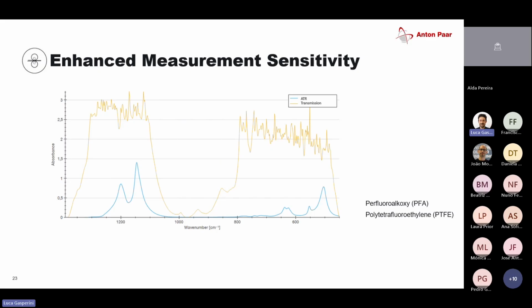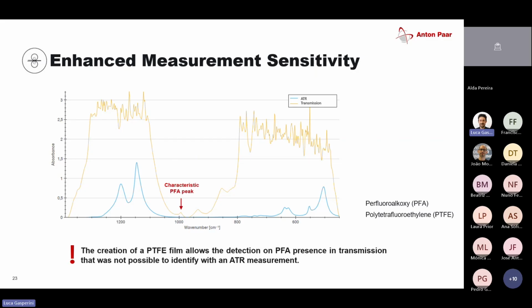Then here I brought an example. So if I compare the same sample on different measurements, you can see the different sensitivities. Here at the bottom, the blue FTIR spectrum corresponds with an ATR measurement, and the yellow one with the transmission. If I want to verify or identify something with ATR, I have a much easier time, because I get very smooth peaks, enough information to do a qualitative analysis. But let's say I want to quantify something, then the transmission comes in here.